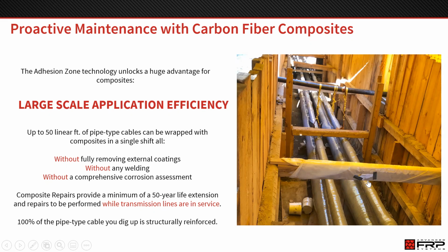The key to it is, like I said, the adhesion zone technology. We can encapsulate 100 feet of feeder lines, and we only remove the coating and grit blast 3 feet on either end. So 94% of that surface does not have any surface preparation outside of just cleaning off some dust, dirt, and debris and smoothing it off. So this is cutting down over 90% of your surface prep. It's also crucial because a lot of these feeders have been in the ground for, like I said, 20 to 50 years.